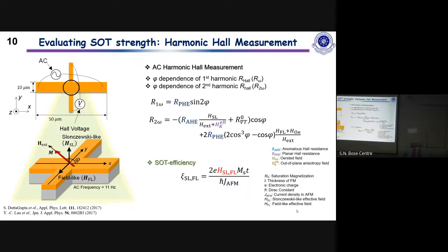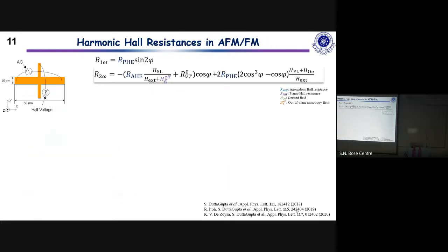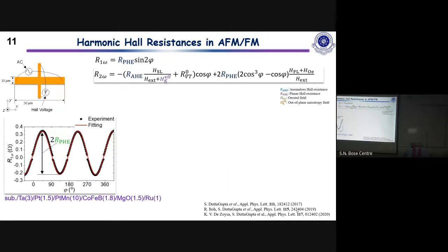So if we measure both the first and second harmonic, and if we know this planar Hall, anomalous Hall, and all of these terms, then one can evaluate the effective magnetic field that is coming out from the application of the electrical currents or the spin Hall effect. And then one can define a parameter which is called the efficiency of the spin-orbit torque, given by this formula. So this is our experimental data.